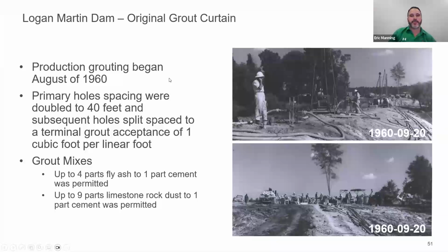So as I mentioned, the original grout curtain I would consider to be pretty deficient for these reasons. The primary holes originally in the test section, prior to the construction of the embankment commencing, the design for the test section was on 20-foot centers, and then the volumetric criteria was 0.5 cubic feet per linear foot to achieve closure.